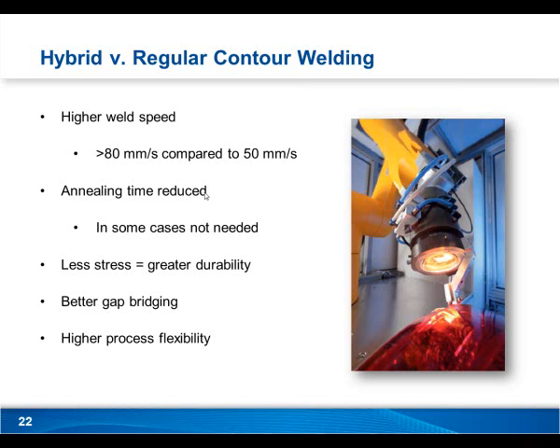Like I mentioned earlier, because of the volumetric heating, we're not shocking the plastic quite as much. The laser isn't hitting cold plastic, it's essentially heating preheated plastic, and because of that you're not going to get that thermal load and thermal shock. Better gap bridging, again, the polychromatic halogen radiation is softening that plastic and allowing us to bridge the gap easier because that plastic is going to form into the housing. And then higher process flexibility. Like I mentioned, it all comes back to the halogen radiation preheating the lens, and that gives you a lot of extra process flexibility.